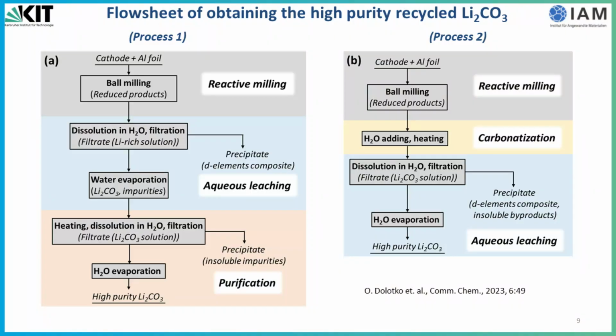While tuning our technology, we developed two processes. After the reactive milling, the reduced products are leached with water in the aqueous leaching step. As a result, we obtain lithium carbonate with some level of impurities. Therefore, an additional purification step was introduced, where we obtain high purity lithium carbonate.